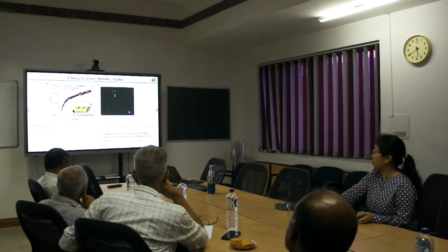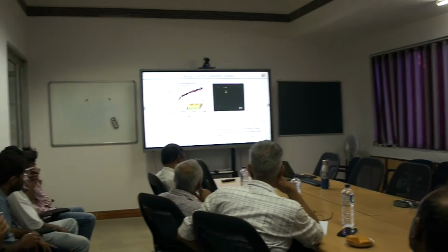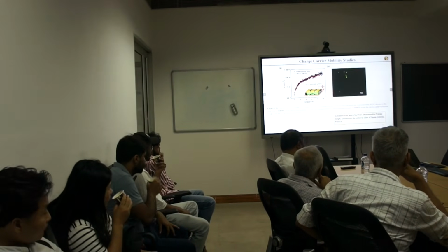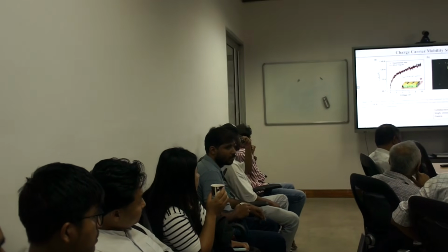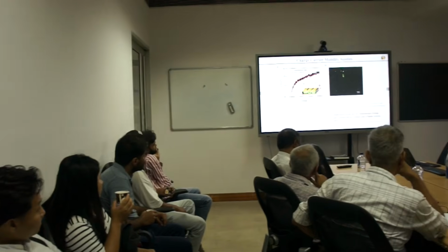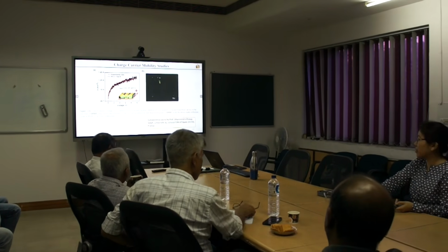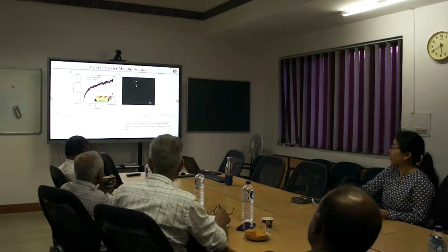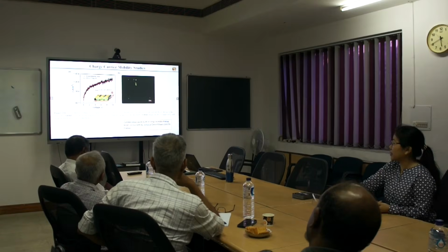In this JV plot, current density versus voltage plot, we obtain a semi-log graph, and using the Mott-Gurney equation, the hole mobility of the compound was found to be in the order of 10 to the minus 5. So even though this compound showed a narrow mesophase width, it showed a columnar mesophase, and we calculated the hole mobility to be this value.